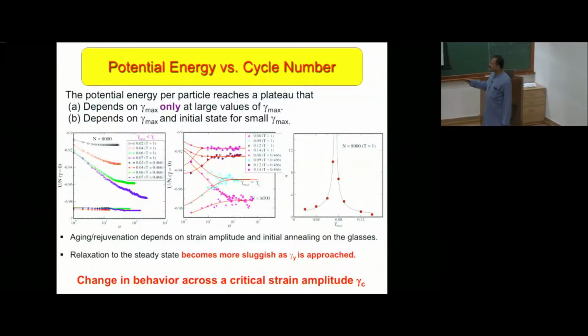So this is now starting with small amplitude, 2%, 4%, 6%, 7% strain, starting with the poorly annealed glass. What you find is that in all cases, the energy cycle to cycle of the glass keeps decreasing, right? And something like that happens also for the well annealed glass, but it's so small that you can't really say anything. But it's important to have that comparison, because you see that the two energy curves fail to meet however long you simulate, right? On the other hand, if you go a little bit above, starting from 8% going to 14% strain, even for fairly short runs, you see that you forget initial conditions.